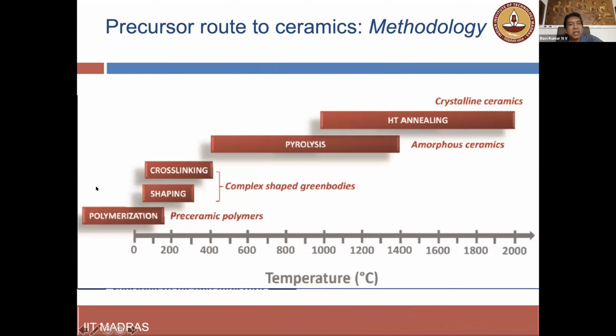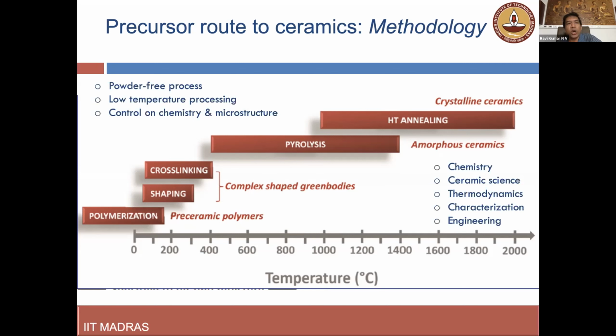All our precursor synthesis, shaping and cross-linking happen in the temperature range between room temperature and around 400 degrees Celsius. The pyrolysis can continue beyond 500, 600 degrees Celsius to around 1200 and 1300 degrees Celsius, depending on what kind of ceramics we're dealing with. Of course, when we have to do annealing to get highly crystalline ceramics, we can go as high as 1800 to 2000 degrees Celsius. So this is the kind of temperature range that we generally deal with in the structural ceramics that we are working on.